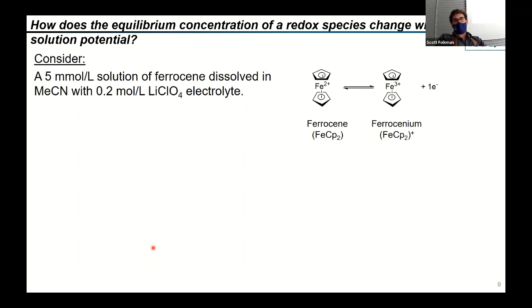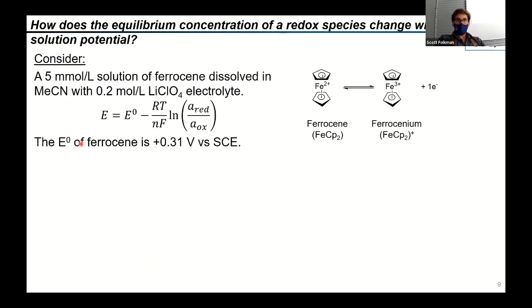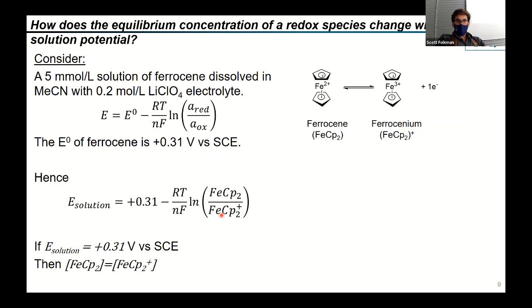So let's consider a solution of 5 millimoles per liter of ferrocene dissolved in acetonitrile with 0.2 moles per liter of lithium perchlorate as an electrolyte. Again, we have this relationship that I described earlier, and we can go look up the standard potential of ferrocene and see that it's plus 0.31 volts versus saturated calomel. And so we can rewrite this equation to put plus 0.31 in here, and it's the ferrocene versus ferrocenium ion. So we know at plus 0.31 volts, under equilibrium conditions, these two values will be equal to one another.